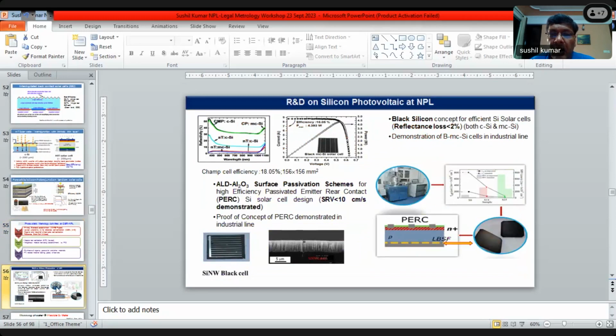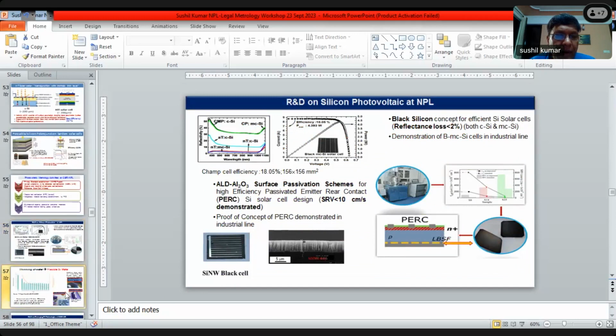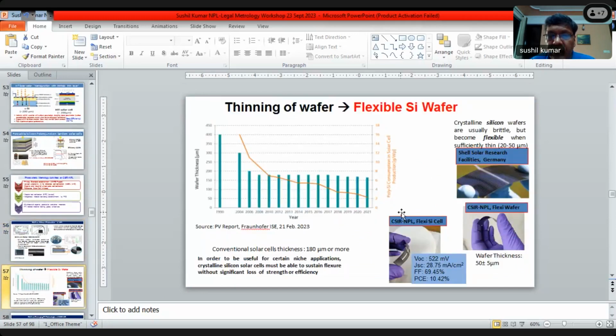This is our R&D on silicon solar cell. We have made 6-inch by 6-inch silicon solar cell with 18% efficiency with the latest concepts. The PERC solar cell with nano texturing in different configurations. Even thinning of the wafer we do, to a smaller thickness, because this is how the technology is evolving with time. Lighter weight means lesser use of material. The current technology is 180 micron, and we are working with 50 micron, so one-third thickness of silicon will be needed, and this becomes flexible up to a certain extent when it goes thinner.